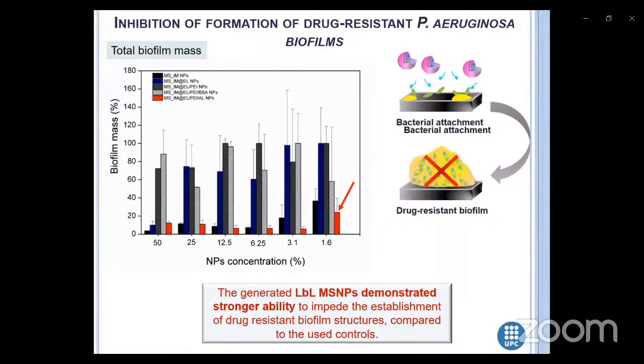The enzyme broke down the alginate and impeded the bacterial attachment and the biofilm formation. Meanwhile, the imipenem eliminates the bacteria. To highlight the importance of the enzyme, we used non-active protein as a control. No biofilm inhibition properties was observed.